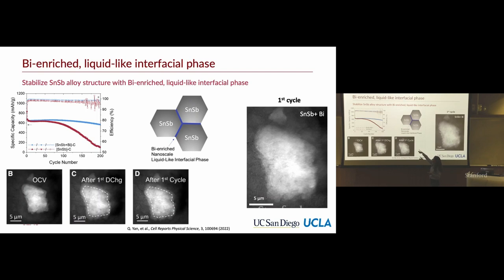The blue one is the stable capacity with the bismuth. The red one is just ball milling without the bismuth, but with carbon. And you can see it falls after about 100 cycles, it really decreases. And so there's still images here. There's a movie as well here. You can see there's an expansion during the lithiation of these materials, just like we had in the nanoporous material, and it was a continuous growth of expansion rather than, like in the dense tin, a burst expansion. And you see no cracking at all.